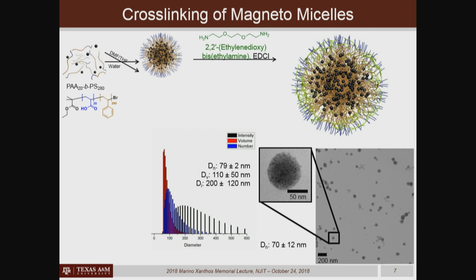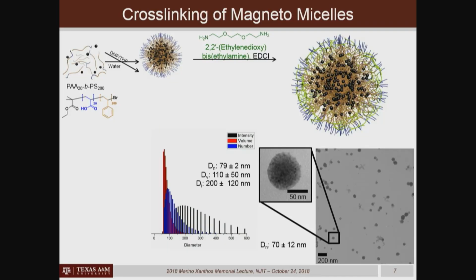This is what we wanted to make, and it was remarkable when Adriana then collected the transmission electron microscopy images. She found first that the particles were fairly uniform in their sizes, and when she zoomed in and, say, evaluated a single particle, you can see the zoomed in image here illustrates heterogeneity in contrast. And that heterogeneity is due to the heterogeneity in the presence of the inorganic particles, which don't allow for electrons to be transmitted, and organic material that's not so good at blocking the electron transmission. And so we see these dark and light regions.